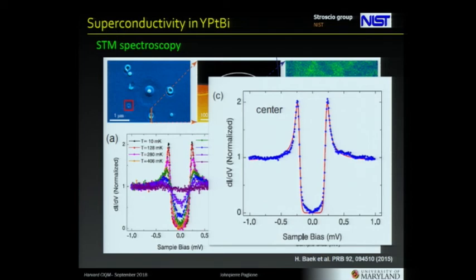We're still working on this pair breaking, trying to understand that, and just doing substitutions to try to see how we can control this state. The palladium system is more interesting because Tc basically doubles. You can go to 1.5 Kelvin, and it's a little more accessible. But those crystals seem to be a little bit lower quality. So when you try to do penetration depth and so on, we see some weird features which aren't so clean. So we're still working on that.